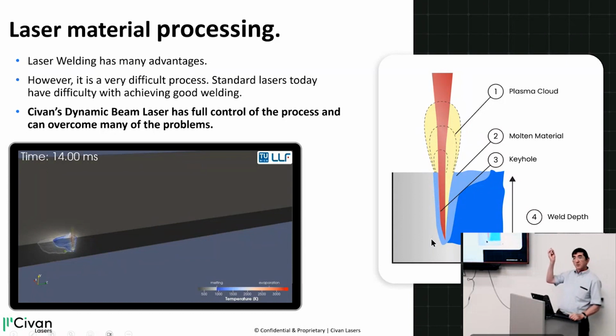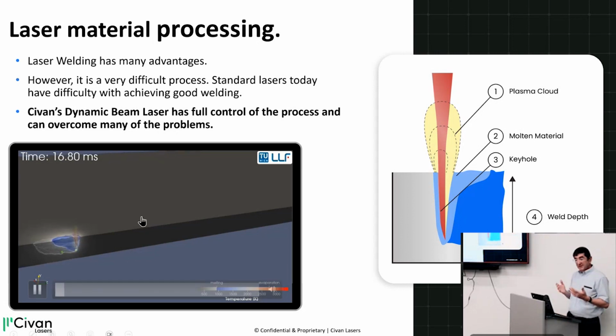Okay, so you create what's called the keyhole. The keyhole is really where you have some gas inside the molten material. So you have the melt pool with the molten material, and inside the melt pool, you have the keyhole where you have gas, and the laser can penetrate through the gas and get really deep into the material and have deep welding without having a very large heat affected zone. The heat doesn't spread to the side so much. And it is all happening very, very quickly.